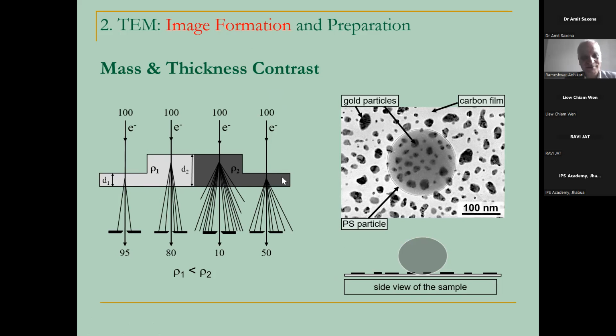And this is the sample thickness. And then rho 1 is the lower density, and rho 2 is the higher density. So if we have electrons which pass through the thinner substances, and here the same electrons pass through the thicker objects, we can imagine that when the electrons pass through the thinner objects, most of them will pass through. While if the electrons pass through the thicker objects, many of them will be scattered.